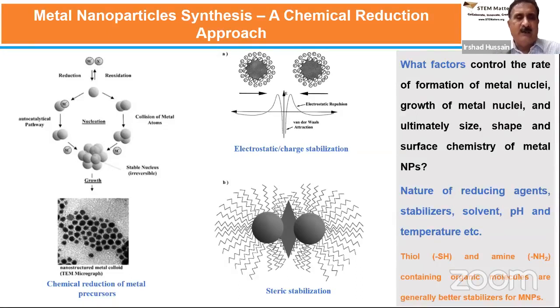In this case, what we do is we start from metal salts and then reduce these metal ions with certain reducing agent into metal atoms. And these metal atoms, they have huge surface energy, and due to electrostatic interaction, they would immediately come together to make the smaller nuclei, millions of these nuclei, depending on the concentration of these metal ions in the solution. So if we let these particles grow, then definitely they will end up in some macroscopic materials.